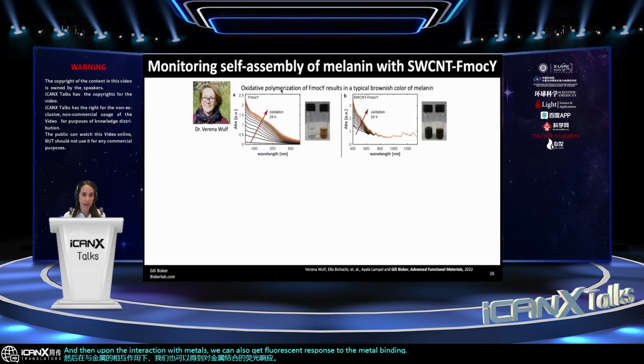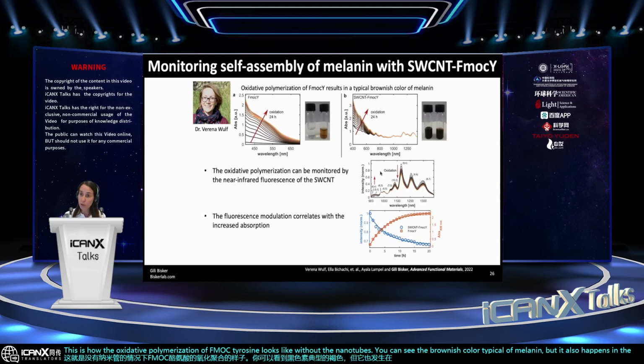This is how the oxidative polymerization of FMOC tyrosine looks like without the nanotubes. You can see the brownish color typical of melanin, but it also happens in the presence of carbon nanotubes, as you can see here. We can also track this enzymatic oxidation and the self-assembly of melanin from the near-infrared fluorescence, as you can see here. As the oxidation takes place, there is a decrease in the fluorescence intensity. And if you plot both the increase in the absorption and decrease in the fluorescence, we can see that there is perfect correlation between these two processes.